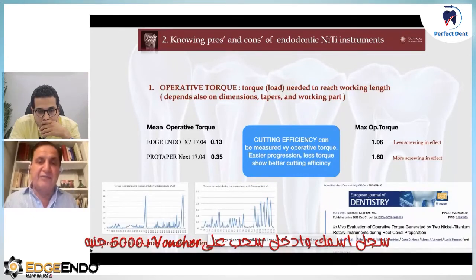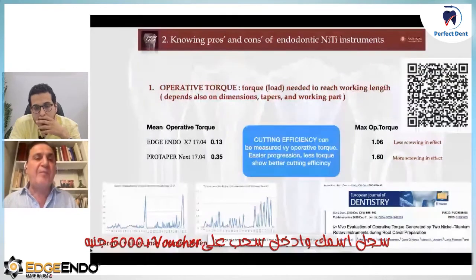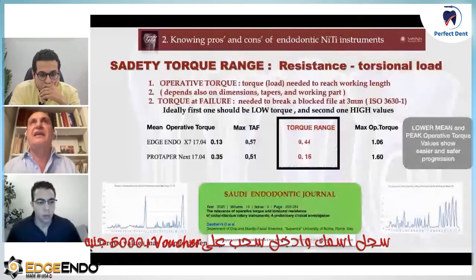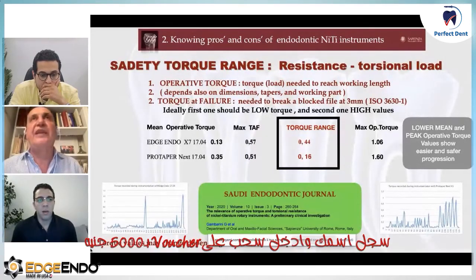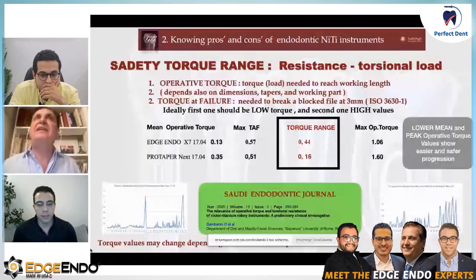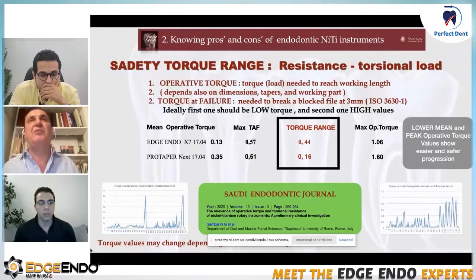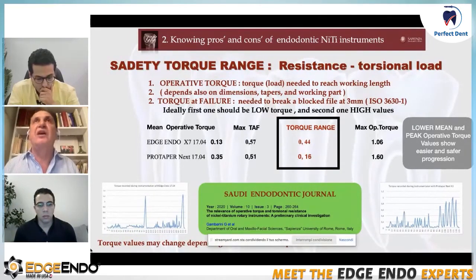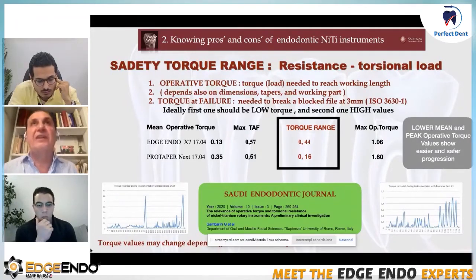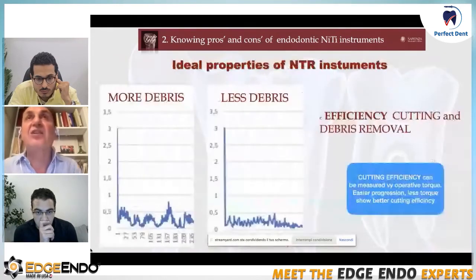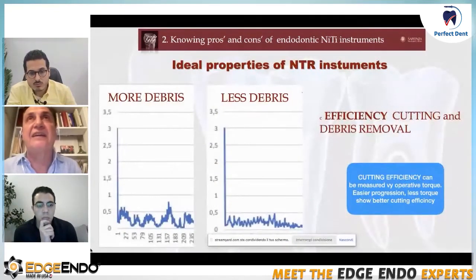But also, if we compare the operative torque with the torque of failure, the torsional resistance, we can make a new test, which in this article we call torque range, meaning that if the resistance of two files is the same but the operative torque is different, the file with low operative torque, like the X7, has a wider safety range during clinical use in a complex curvature. So it is quite an interesting point here, because no one has ever evaluated this before. And I think this is mainly due to the properties of the alloy and the design of the instrument. As Dr. Mohamed told you before, please use a lot of irrigant, and I totally agree with you.